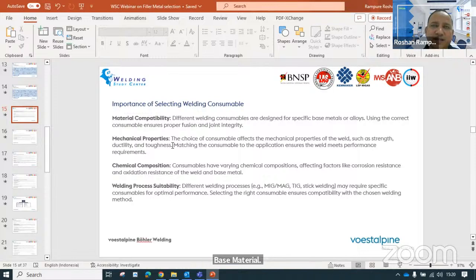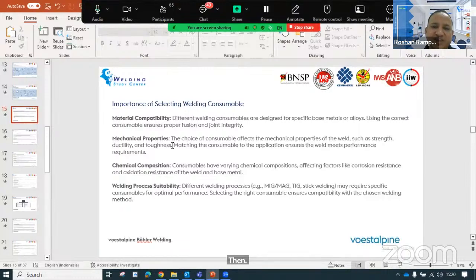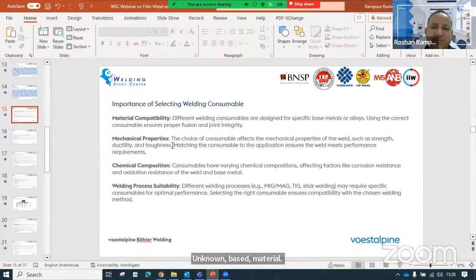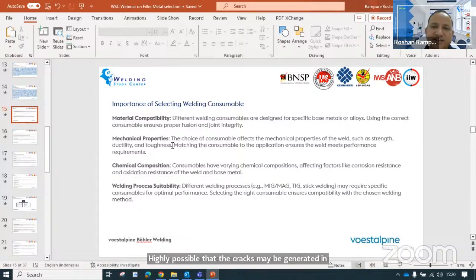Now, when you say that there is a crack generated during welding, then the most common reason for such crack generation during welding of unknown base material is that it may be a high carbon containing base material, and when you do the welding without following a proper procedure, then it is highly possible that cracks may be generated in the welding. The reason is if the base material has very high carbon content or very high levels of impurity elements like phosphorus and sulfur and other tramp elements, then they will segregate during solidification and they can cause cracking.